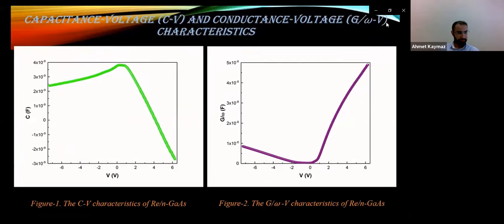On the other hand, contrary to the forward bias CV characteristics, the conductance characteristic, which is given in figure 2, increases with increasing bias voltage and reaches a maximum value at the strong accumulation region. In other words, the conductance characteristic increased rapidly and reached its maximum value, while the CV characteristic reached its minimum value in the strong accumulation region. It is known that this situation is caused by the inductive behavior of the MS-type structure.